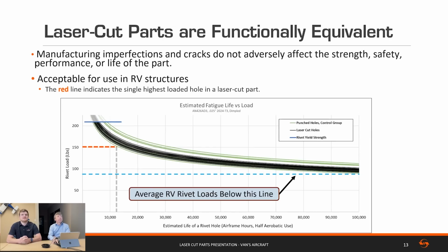So this has a projection from these data points based on how they will perform under different loads. In fatigue, as the stress or the load is reduced, the life dramatically increases. This is, again, that group of flush riveted 0.025-inch thick aluminum samples. And we can see how these data points and their predictions versus load dramatically increase to completely unreasonable numbers. This chart ends at 100,000 airframe hours of half aerobatic use. And if we look at this blue line, that is showing that the average RV rivet loads are below this line. In reality, the average loads are far below that line.